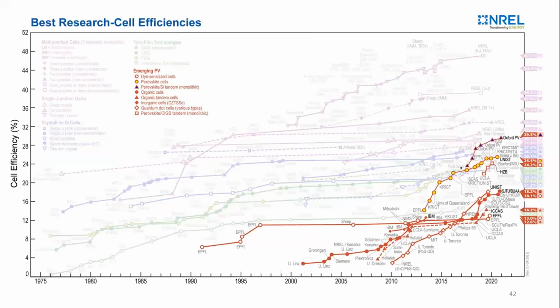Let me show you the state of the art of this perovskite solar cell. You can see that perovskite now can reach up to 25.5% efficiency with only perovskite. If we combine perovskite with silicon as a tandem structure, it can even go up to 30%. So now the research community is in the process of commercializing this perovskite solar cell, and this is based on lead.